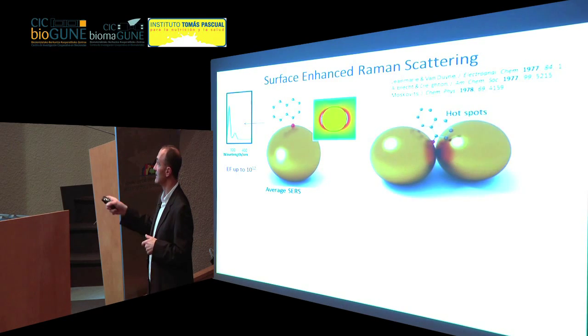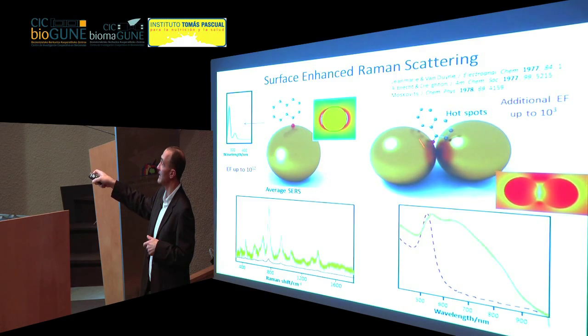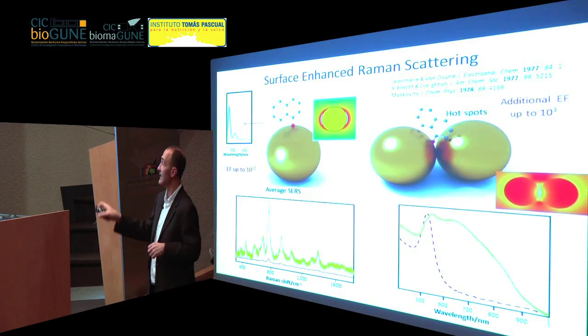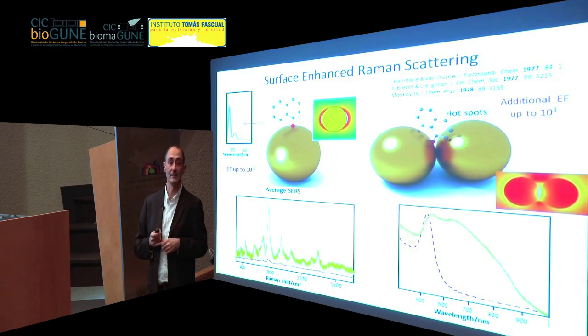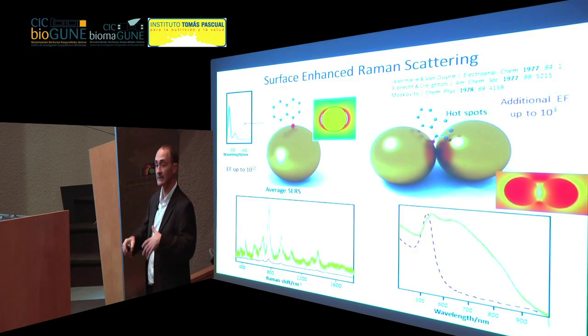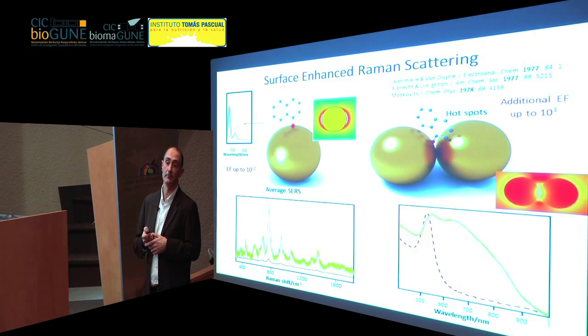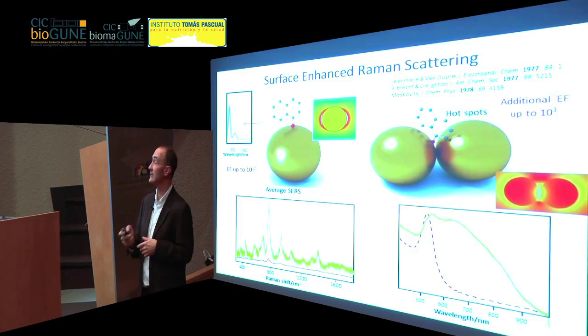You can still even increase the enhancement by bringing particles together, because then you form what is called a hotspot, meaning that the plasmon of one particle and the plasmon of the second particle overlap at the gap between them, and then you have a much higher field in between, about 1,000 times higher than usual, and then you get even better sensitivity than with single particles.